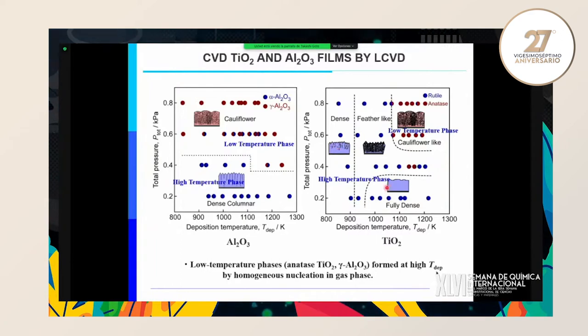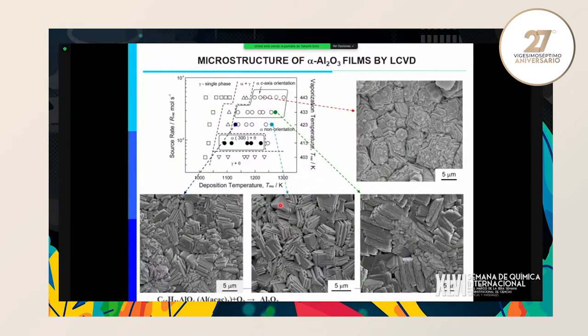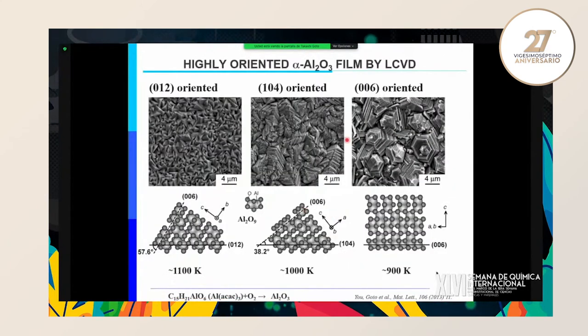But by using conditions with less nanoparticle formation, at low temperature and pressure, we can prepare dense alpha alumina at slightly low total pressure, and we can make it at low temperature, around 900 K, which is almost 200 to 300 lower than conventional CVD. And by choosing more CVD conditions, we can find conditions to prepare specifically oriented alumina films. Then we can find 006 oriented or 104 oriented